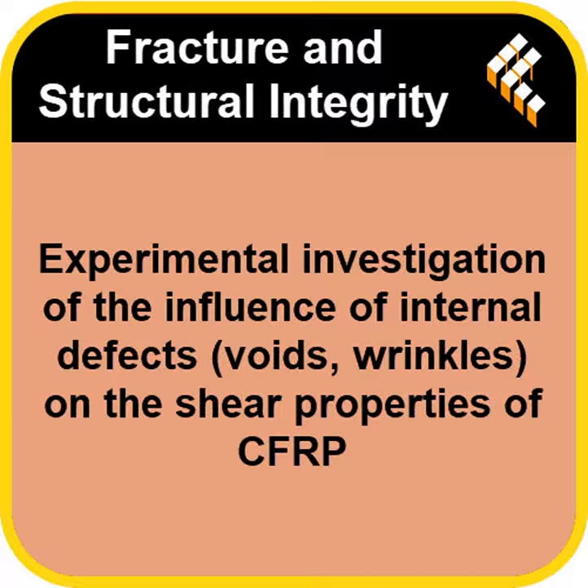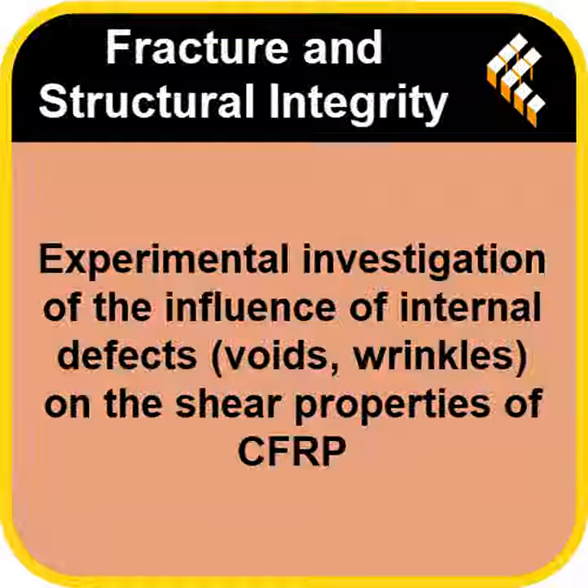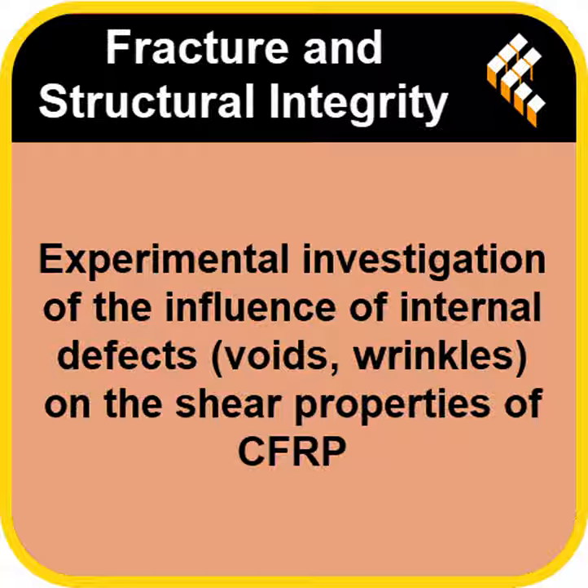No. How do they explain that? The interpretation is that under this type of shear loading, the failure isn't primarily driven by tiny stress concentrations at the void edge. It's more influenced by the overall reduction in load-bearing area caused by the void. So the amount of material missing, the 5.3% area, was the dominant factor, not the shape of the missing area. That seems to be the case here. The shear failure mechanism might be less sensitive to those sharp geometric features compared to, say, pulling the material apart in tension. That is fascinating.